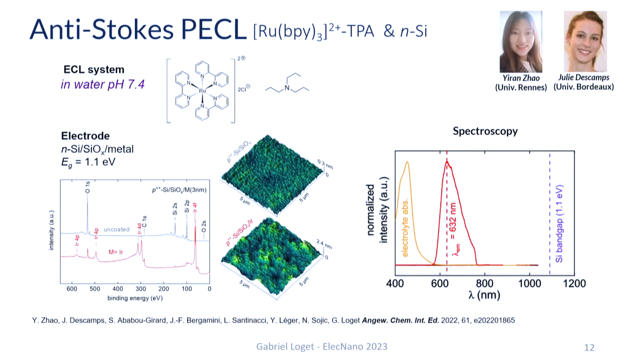On the spectroscopy data, you can see the band gap position of silicon. This is very important because, as I mentioned, if we want to use this material as a photoelectrode, we have to excite it with an energy higher than 1.1 eV, which is its band gap. So we have to work in this region. This is why we chose an excitation wavelength of 850 nanometers, which is in the near IR, invisible to the human eye, and sufficiently spaced from the emission and the electrolyte absorption. So we are sure that there won't be any fluorescence process occurring during our experiments.